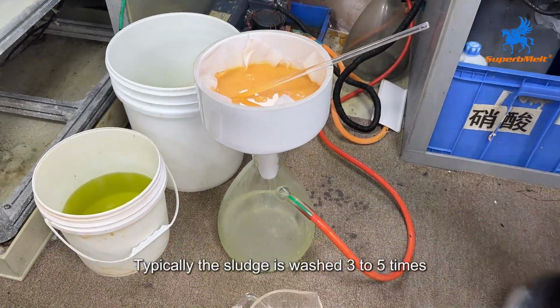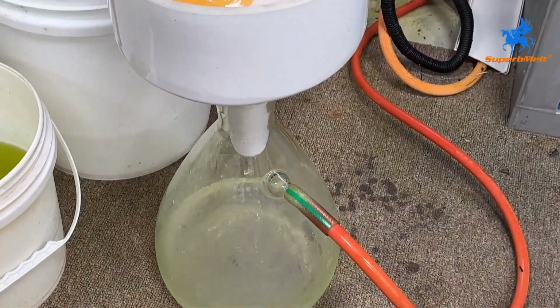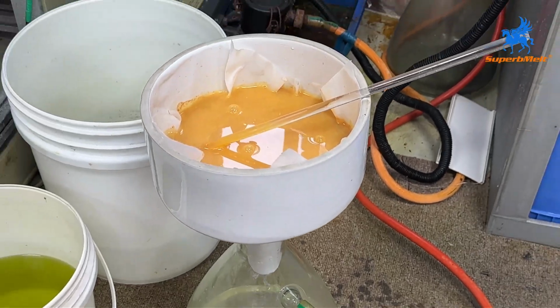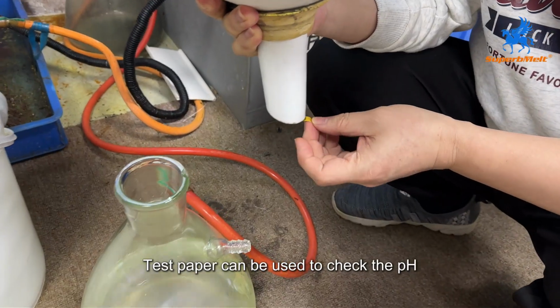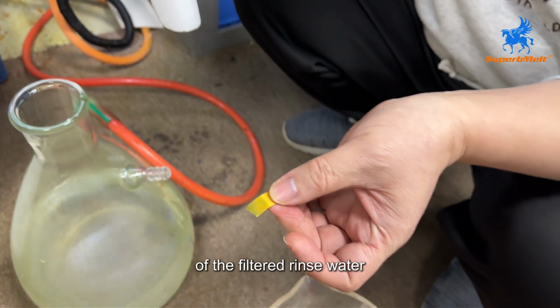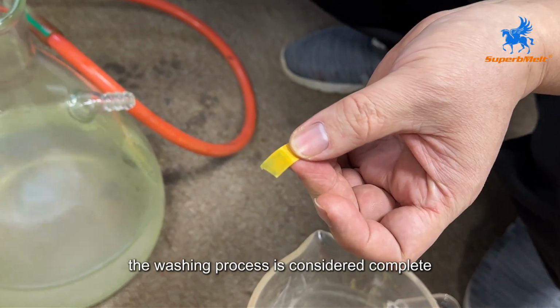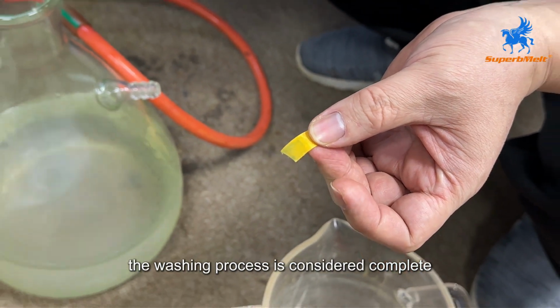Typically, the sludge is washed 3 to 5 times. Test paper can be used to check the pH of the filtered rinse water. When the result is neutral, the washing process is considered complete.